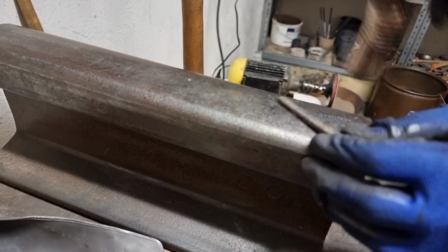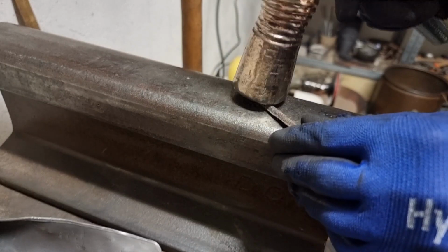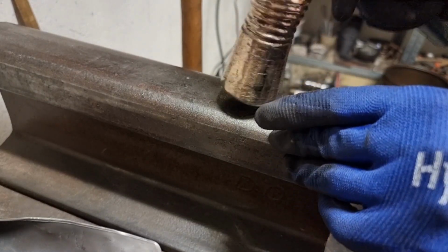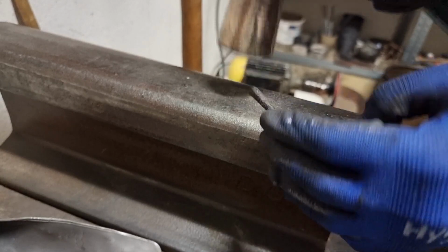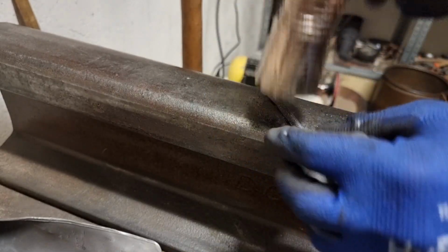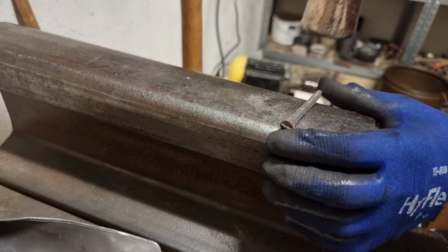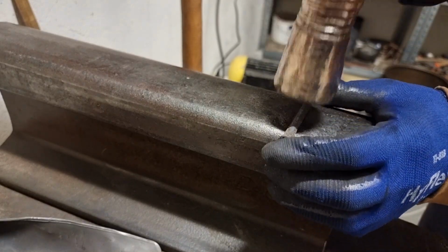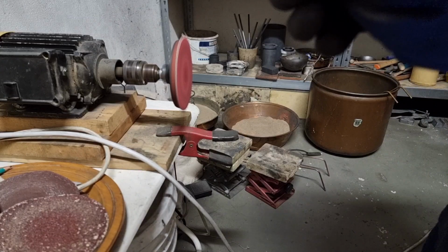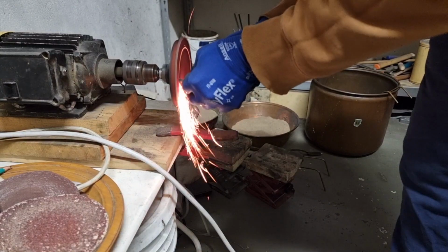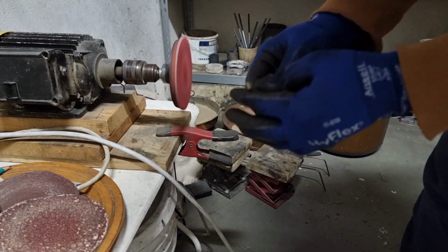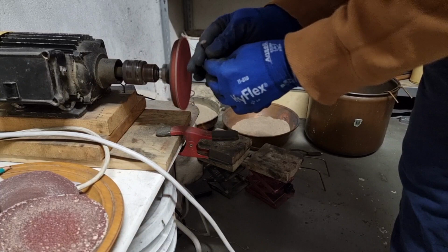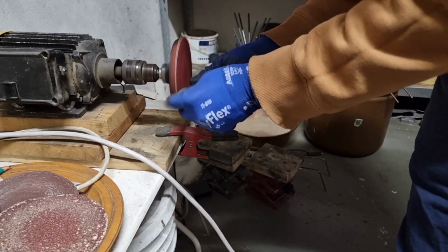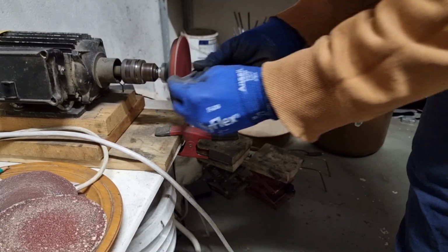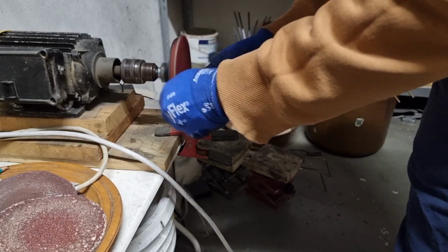After I extracted the nails, I did a quick check with a hammer, so I applied a few punches with a hammer. If the nails would be still pure white cast iron, they would now instantly break apart. But since they don't, that shows that the surface got converted into steel, giving the nails enough toughness to be of usable quality. Another check is, of course, the spark test, and you can see by the white sparks that the surface got totally converted into a form of soft wrought iron, which confirms that the conversion of white cast iron into steel was successful.